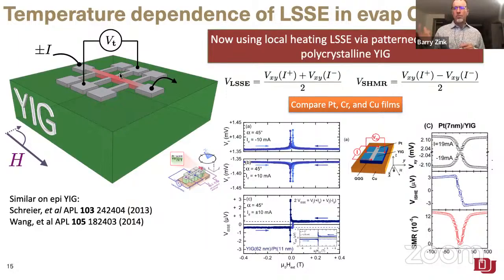So heating effects should scale with the current squared, and so basically if you add the result you get from a positive current and a negative current together and then divide by 2, that should give you stuff that is telling you mostly about thermal effects. So that's what we'll call the spin-Seebeck signal in these experiments.